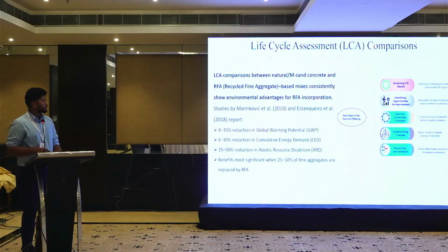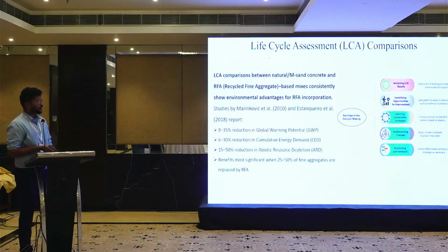LCA comparison. Environmental: by incorporating this RFA, we can reduce global warming potential by 8 to 35%, and cumulative energy demand, CED, by 6 to 30%.